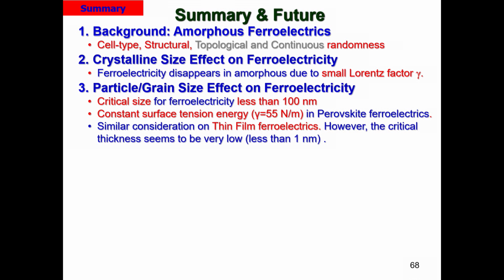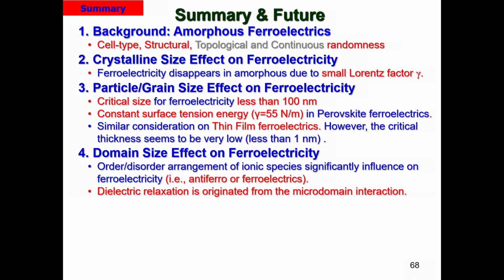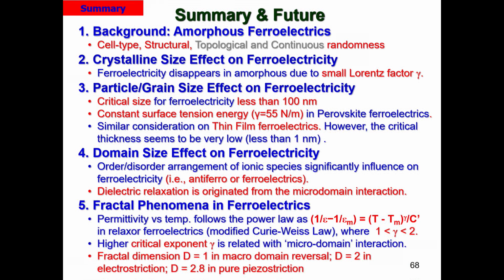The similar consideration applies to thin films, okay? However, the critical thickness seems to be very low, okay? And the domain size effect on ferroelectricity, order and disorder: order becomes anti-ferroelectric, disorder becomes ferroelectric. And the dielectric relaxation originates from micro-domain interactions. And the final one, fractal dimension: if you plot the gamma values of permittivity versus temperature, you can evaluate whether this is relaxor type or normal type and so on. And a higher critical exponent gamma is related to micro-domain interaction.